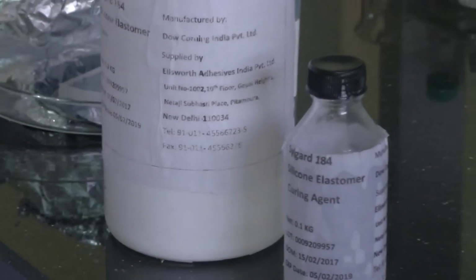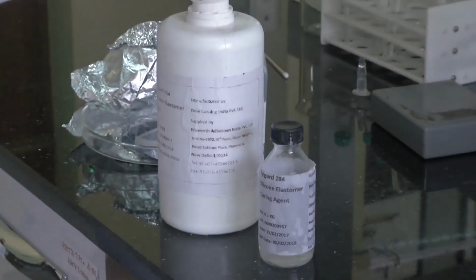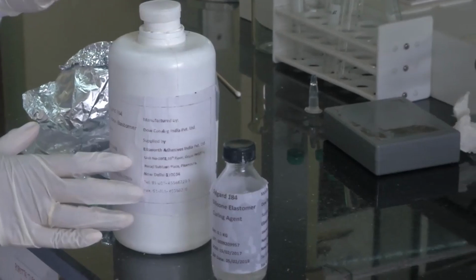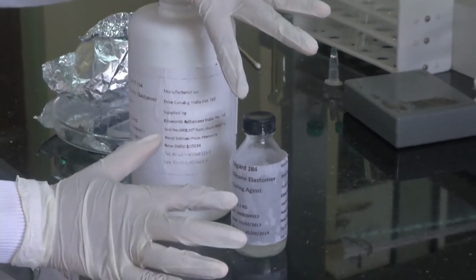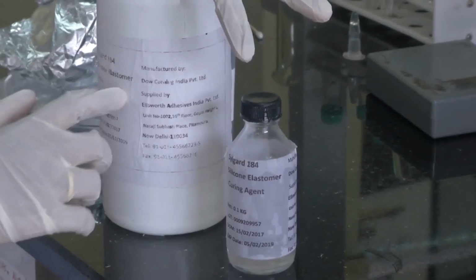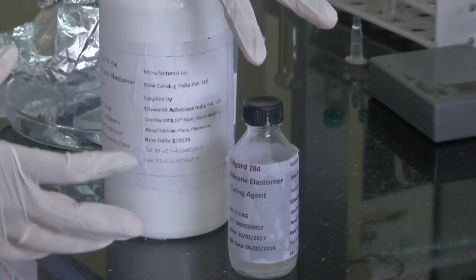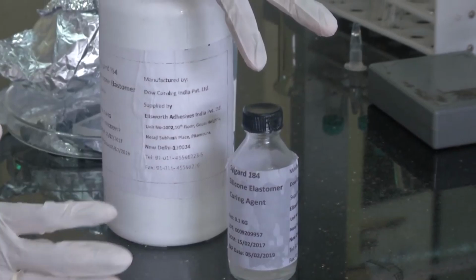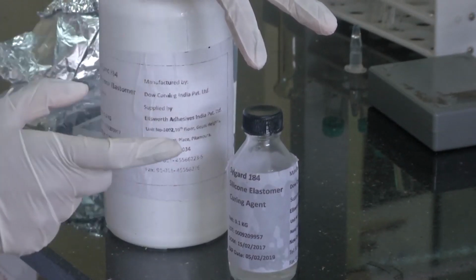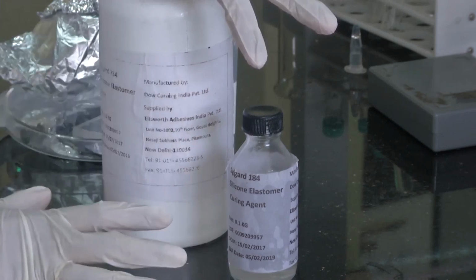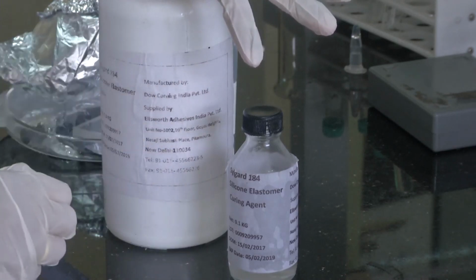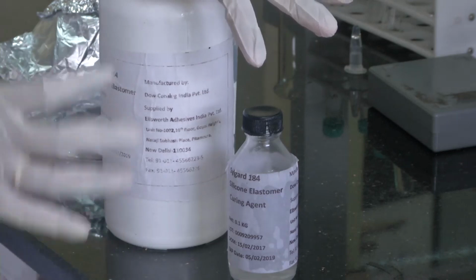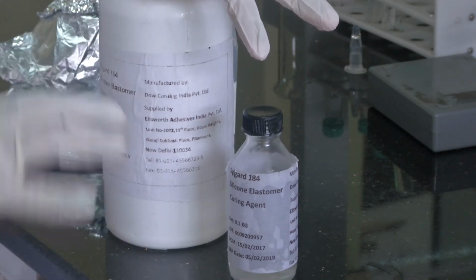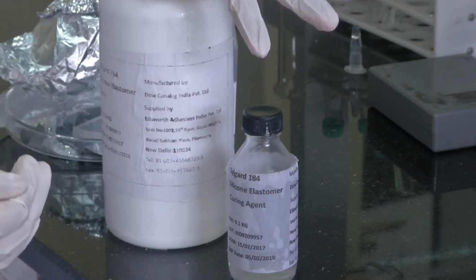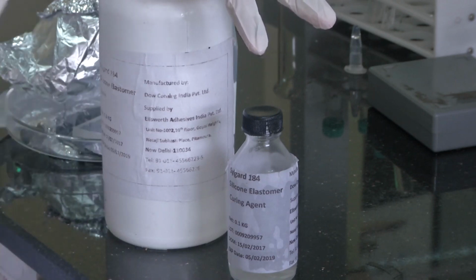So, if you want to make a mold using PDMS, then you might consider buying this elastomer and a curing agent. The elastomer and curing agent are mixed in a certain ratio. This is a 10:1 ratio. In this ratio, when these two are combined, it forms a polymer which can be cured and molded easily. You can replicate micro to nano level features in just a few hours.